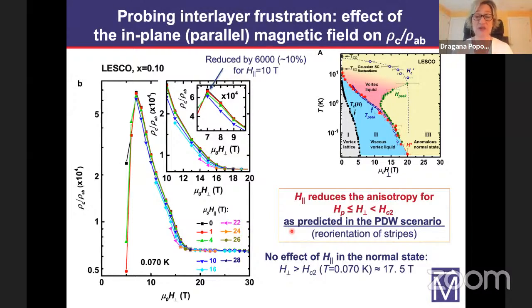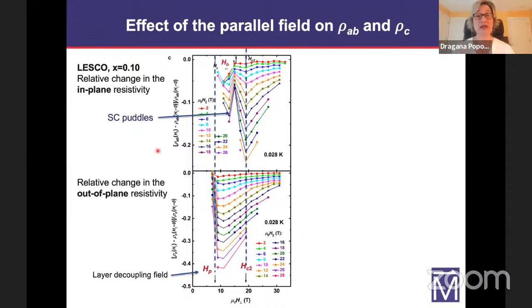But in order to try to understand the effect of the parallel field better, we also looked at its effect on the in-plane and out-of-plane resistivities separately. So here on the top graph, this is the relative change of the in-plane resistivity with respect to its value with zero applied field. So these are the values of the parallel field, and again, as we go through our vortex phase diagram, as a function of a perpendicular field. I hope this is clear.